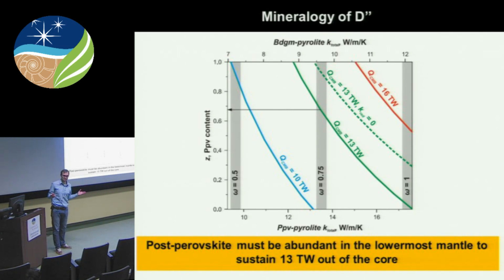And say what you think seismologists should now look for or do with analytical models. So what is shown here is the total thermal conductivity of bridgemanite pyrolite of the mantle that contains exclusively bridgemanite, and here pyrolite that contains exclusively postperovskite. Because postperovskite and bridgemanite have very contrasting lattice thermal conductivities, you can actually model how much postperovskite you need in order to sustain the heat flow out of the core, because the value of heat flow depends on the total thermal conductivity that you have.